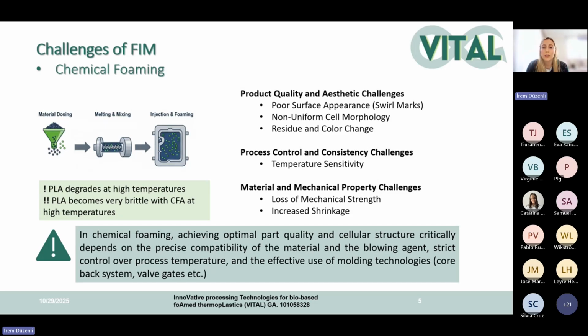In chemical foaming, we have challenges about product quality and aesthetics. With chemical foaming agents, we sometimes get a poor surface appearance, like swirl marks, flow lines, and weld lines, because it's very hard to get optimum parts with chemical foaming agents. Sometimes we also struggle with non-uniform cell morphology and color change, especially in colors other than black. In white, for example, we can see some color changes of the parts.